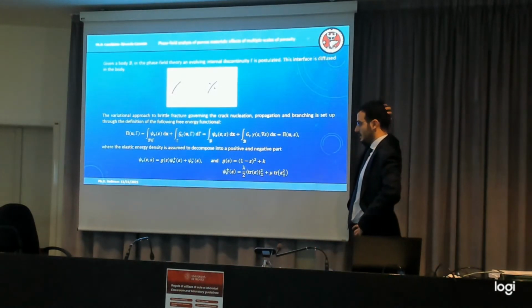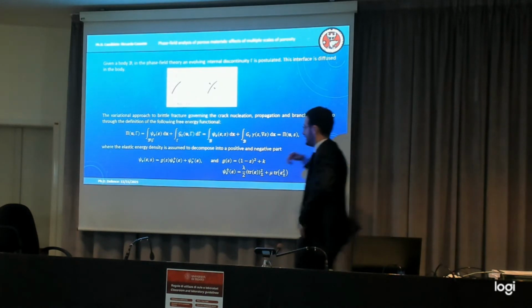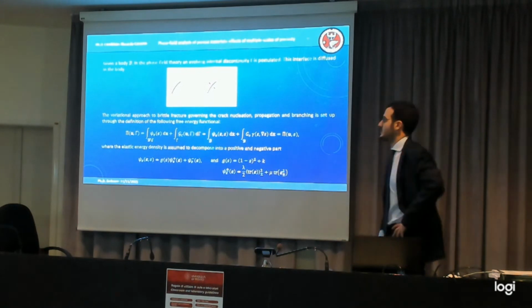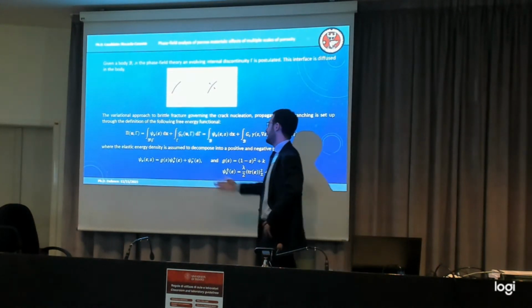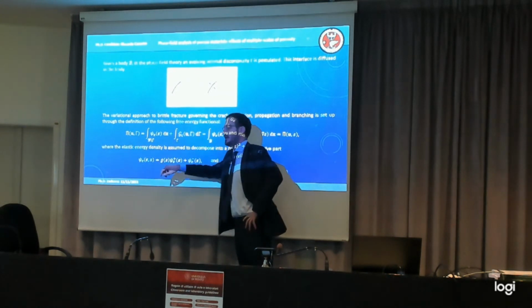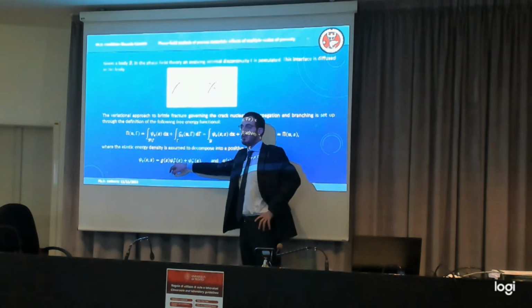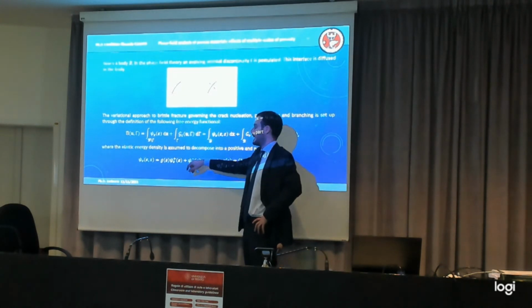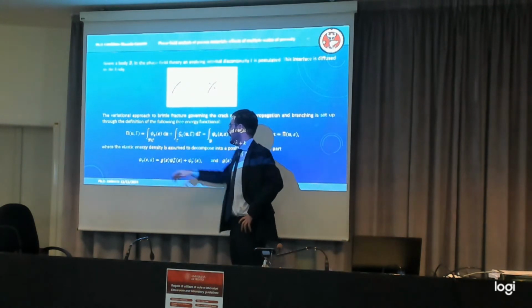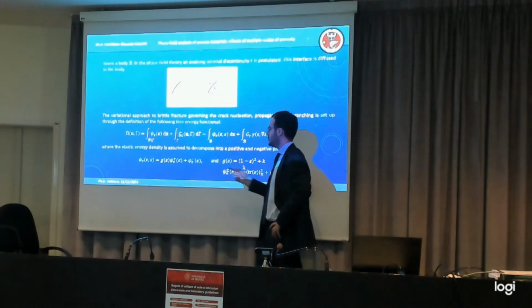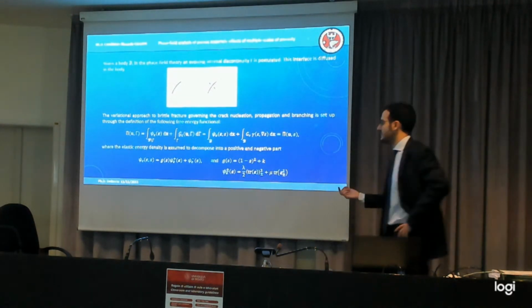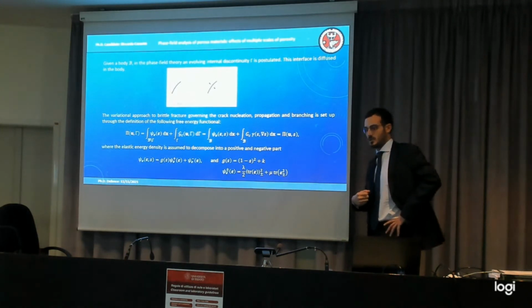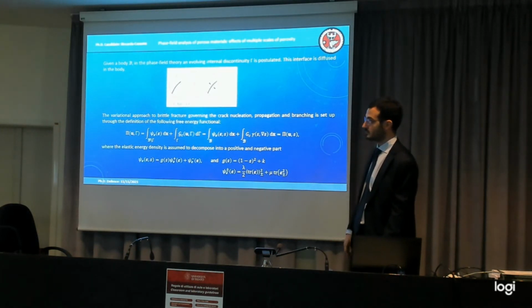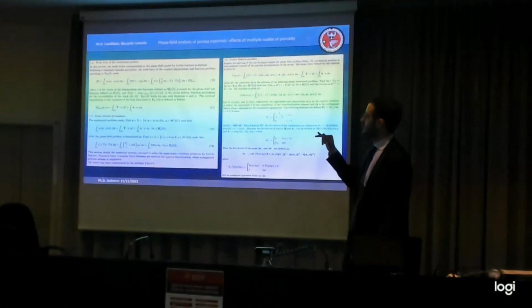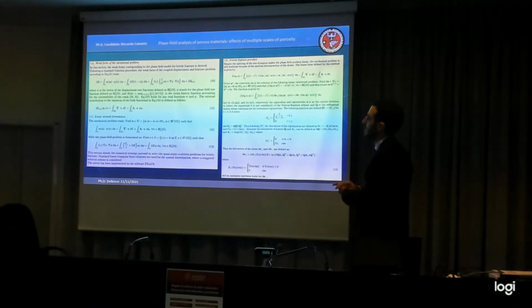A typical assumption that is made in these cases is the one made by Miehe in one of his works in 2010. And well, the assumption is very easy to make. You split up the strain energy into a positive one and a negative one. The positive one is associated with traction, with tension, and the negative one is associated with compression, and then you add a degrading function only to the tension part. So in this way, you're sure that the properties are degraded only for tractions and not in compression. You don't have any rupture under compression. So once you have that formulation, it's very straightforward and easy to develop the variational formulation and the finite element.